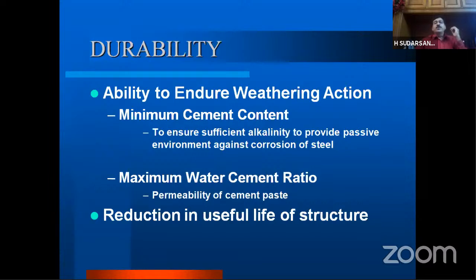Now, if you look at durability, which is very important, durability is the ability to endure weathering action. To achieve this, we have to maintain a minimum cement content so that we maintain the required alkalinity to provide a passive environment against corrosion of the steel. If your concrete is more acidic, the reinforcement steel inside the concrete has more chance to get corroded. So it is always better to see that sufficient alkalinity is there in the concrete to have a passive environment against the environmental conditions, to protect the steel from corrosion.